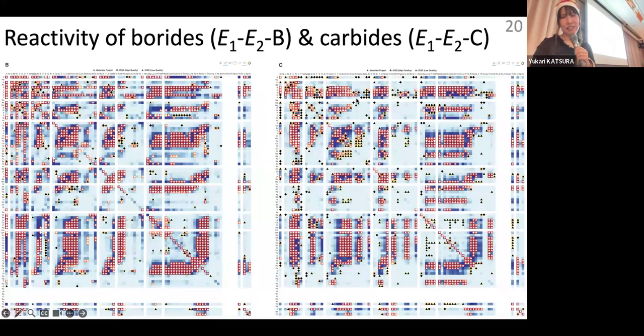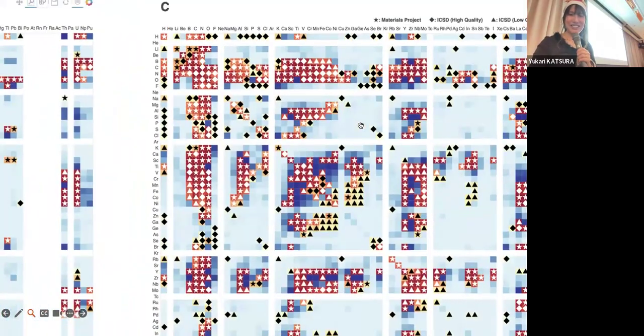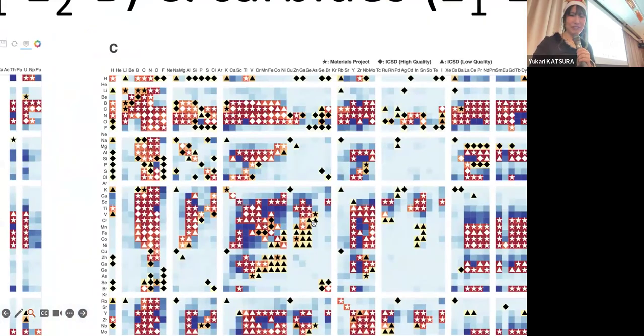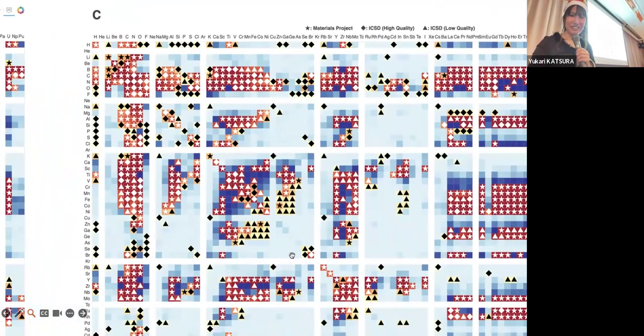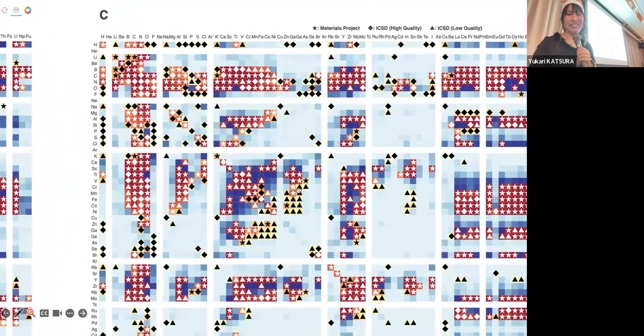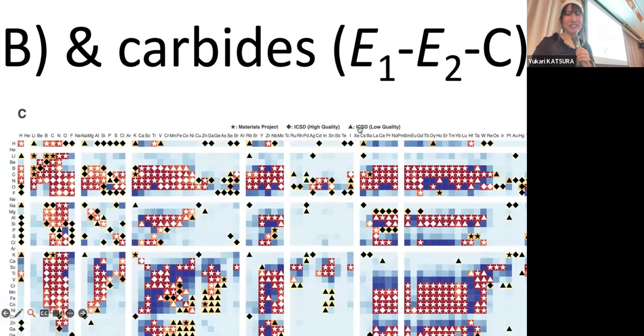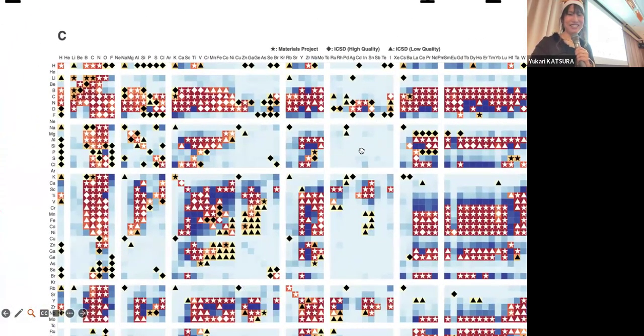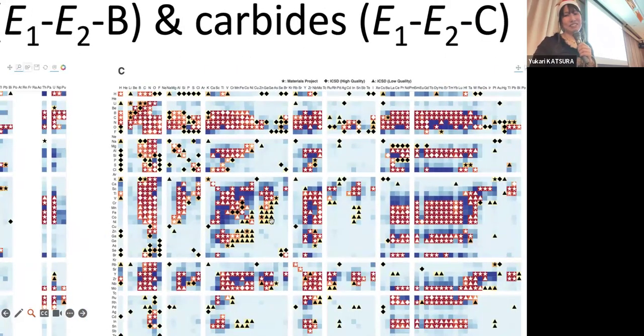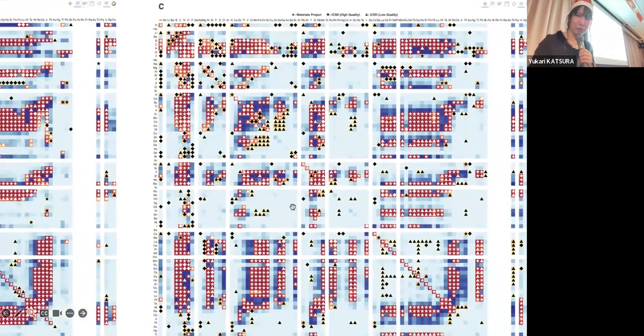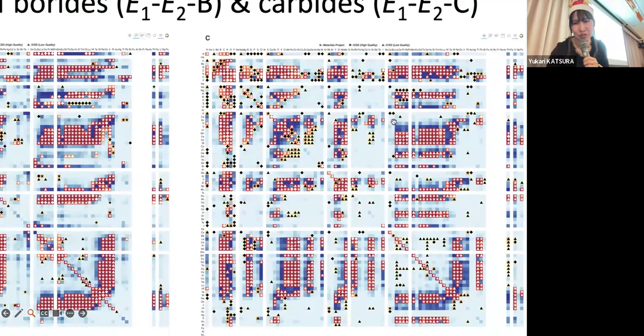And we see the map for the carbides, and these are similar. But there are some yellow ones. These are thought to be low quality in ICSD, so maybe these compositions are not so correct. The machine learning program says no compound forms, and ICSD, the Inorganic Crystal Structure Database, says the structure is low in quality. So maybe for carbides the structure analysis is difficult, but still we can explore new compounds.